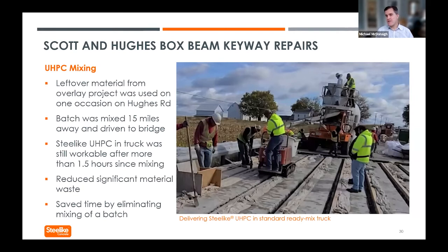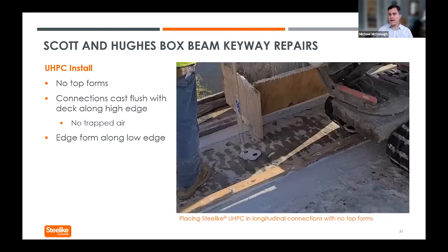So another advantage that was used on the mixing was the material was actually mixed at one bridge and driven 15 miles to another bridge, and was kept alive for more than 1.5 hours, saving the wasting of a batch and the need to mix an additional batch.